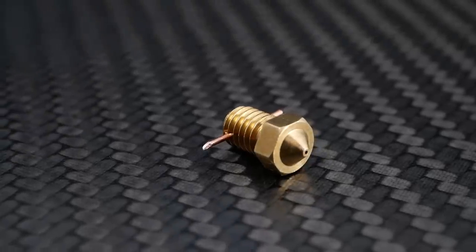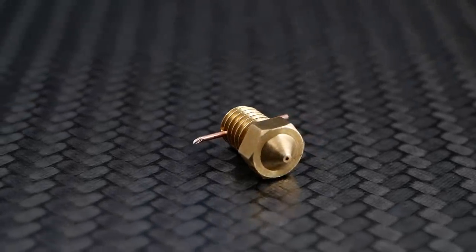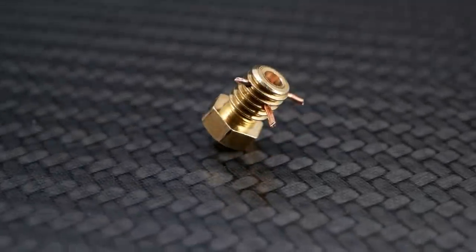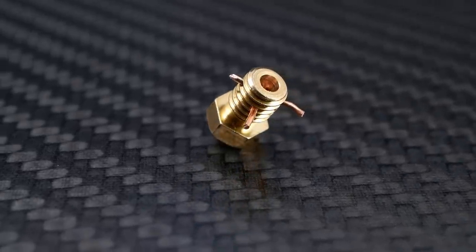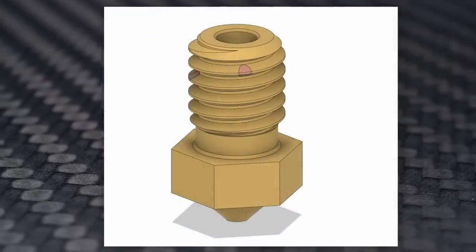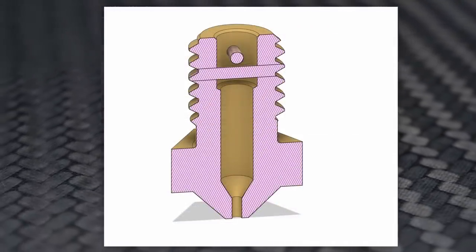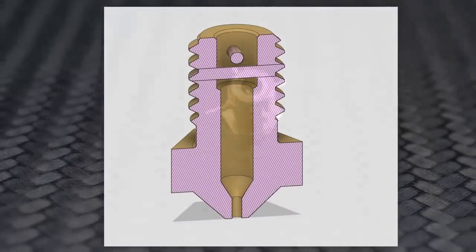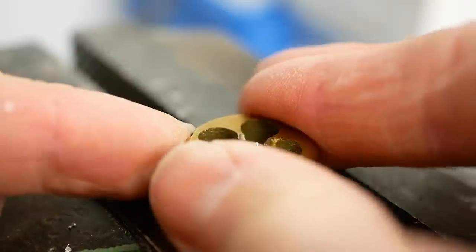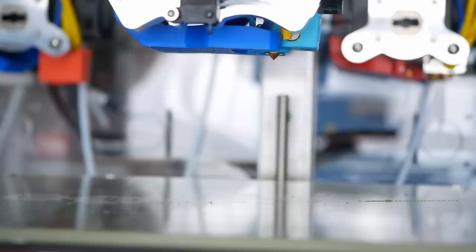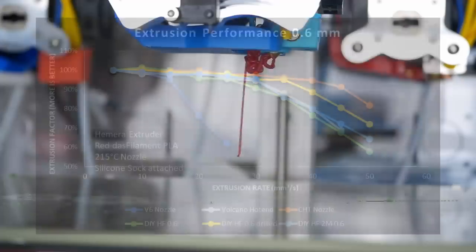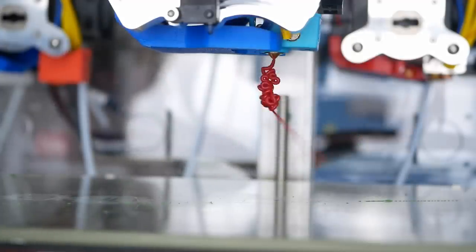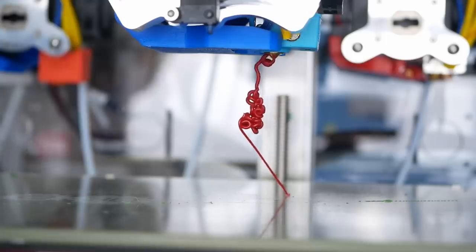You may now ask yourself, if one piece of wire improves the performance that much, well, how would adding two wires perform? That's why I modified yet another nozzle by drilling two holes 90 degrees apart from each other at 1.5 and 2.5 millimeter depth and again soldered wires in and finished it up with a die. This one, interestingly performed similar to the Volcano and the undrilled mesh nozzle. This shows that a second wire on the one side might help with melting. On the other side, it adds additional turbulence and flow resistance, which is detrimental for performance.